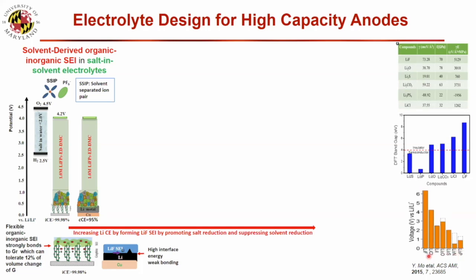So in this talk, we not only mention lithium fluoride on the lithium metal, we also talk about if we form a lithium fluoride on a high capacity cathode like NMC811, it also significantly increases the cycle life. Based on this justification, we think the best way is to form lithium fluoride. But how can we form lithium fluoride? The idea is we need to reduce the anion rather than the solvent, because if the anion is fluorinated, its reduction forms lithium fluoride SEI.